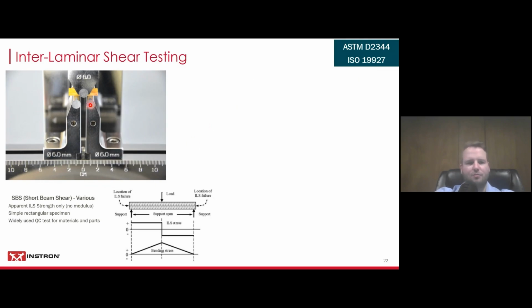So you can run this short beam shear, which is basically a 3-point bend setup, but you're using a very, very narrow separation on your supports on the bottom, and the yellow part here is your test specimen. This is a widely used QC test for materials and parts, and you can use a simple rectangular specimen. You cannot, however, determine your interlaminar shear modulus with this testing.